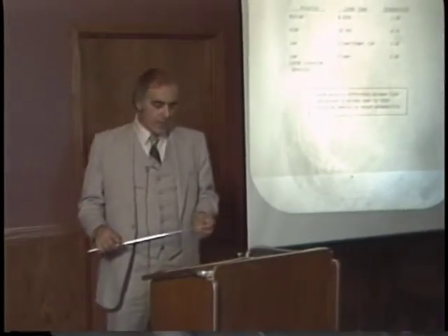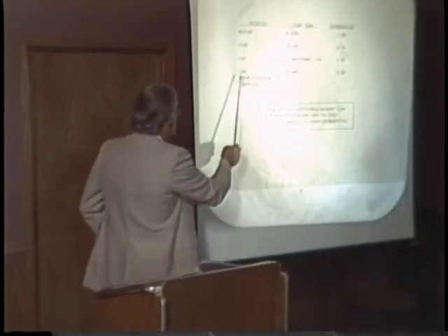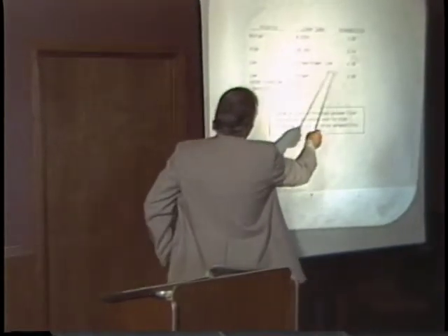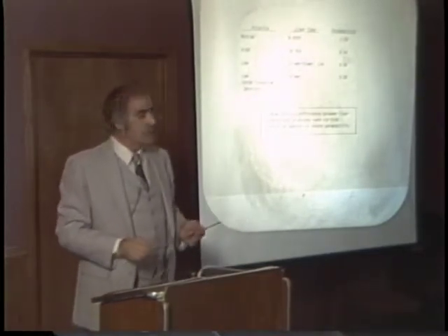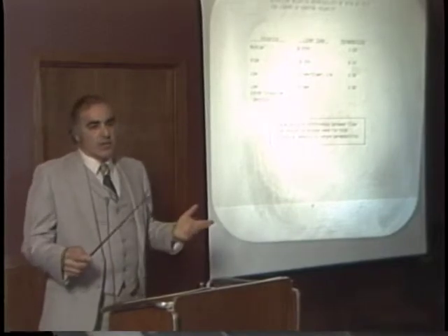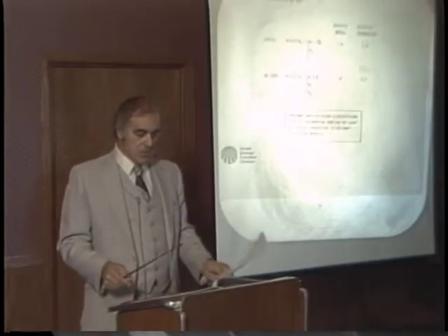The next factor is the effect of polarity. In this particular slide, we're showing a medium, high, and low polarity system, and then the slide you saw earlier where we looked at the low crosslink level of trimer and dimer, and then just trimer by itself, which would be the highest crosslink level. And we can see here that in a low polarity system, it doesn't make any difference on the permeability whether it's highly cross-linked or not. And when we deal with a high polarity system, we have high permeation through the system. And of course, in medium polarity, we have intermediate permeation through the system. So in this particular case, it's fairly straightforward. The ability of the migrant to associate with the polymer has a direct bearing on its ability to move through the polymer. Next slide, please.